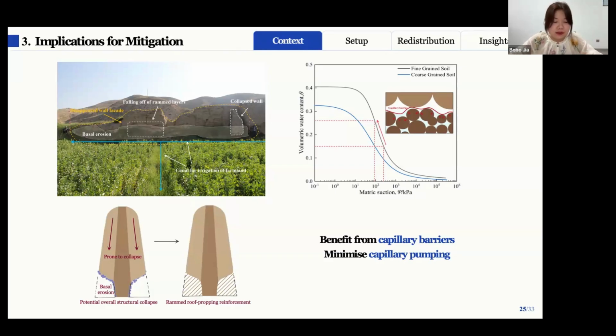As shown in the diagram, when water moves from a fine layer to a coarse layer, the capillary entry pressure of the coarse layer is higher. As a result, water cannot easily enter the coarse layer and tends to accumulate above the interface. In contrast, when water moves from the coarse layer to the fine layer, the fine layer has a higher water retention capacity, which promotes the water migration. This can be seen in capillary pumping.